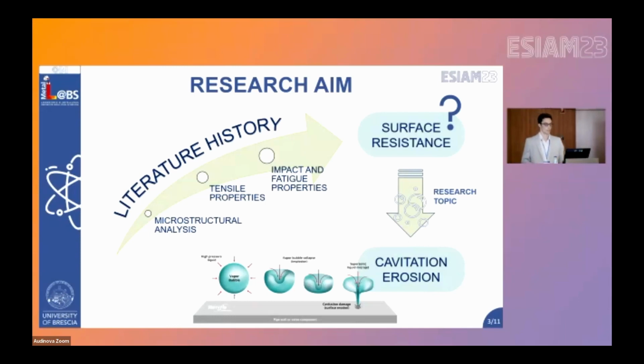cooling insert. In fact, as known, cavitation erosion happens when a liquid experiences rapid changes in pressure, and when the pressure goes below the critical pressure of the liquid, that is related to its vapor pressure, bubbles will form, and when the pressure rises up again, these bubbles will collapse, generating both shockwaves and ultrasonic microjets.